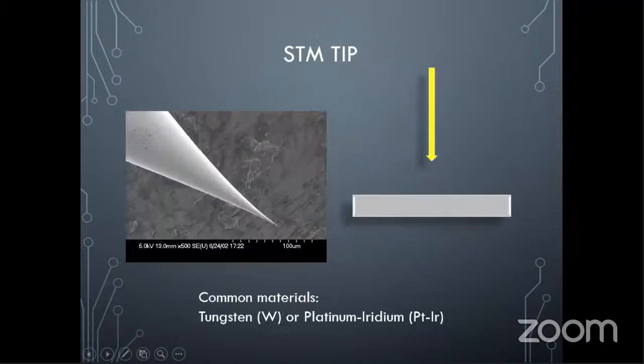Now, the idea behind the scanning tunneling microscope is that you have a very sharp metallic tip, a pin-like structure, where the apex, or the head of the tip, has a few atoms and can have a width of a few angstrom. Now the idea is that if you take that tip very, very close to your sample, but not touching, then quantum tunneling of electrons will happen between the sample and the tip.